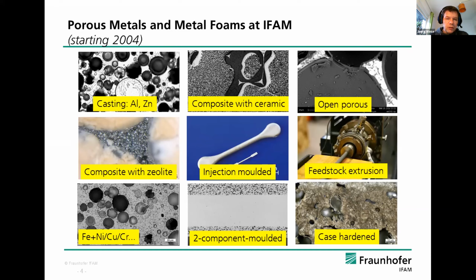And coming to the sintered structures, we later changed to combine the hollow spheres also with steel or iron or other sinterable metals. So one focus in our department is in metal powder injection molding. With this method, you can produce near net shape components made with the hollow spheres. You can also use feedstock extrusion. It's almost the same process, but resulting in other geometries. And those techniques we used for iron combined with nickel, copper, chromium, alloyed steels, and so on.